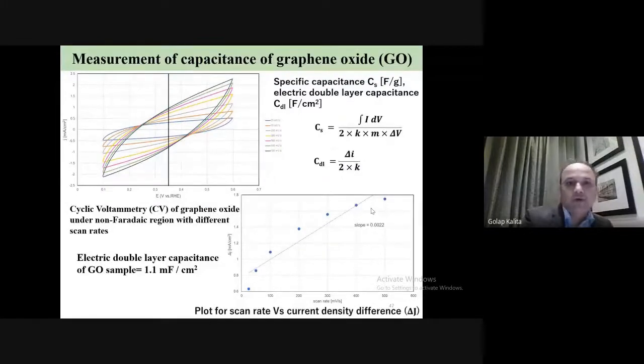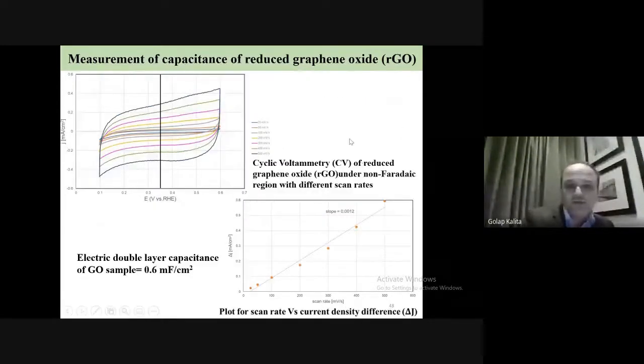Then for the same materials, GO and RGO, we studied the capacitance measurement, and you can measure the specific capacitance as well as the electric double layer capacitance by changing the scan rate for the CV. We measured from 25 to 500 millivolts per second scan rate. In the middle, you see the difference of current, delta I. If you plot this versus scan rate, you can find the electric double layer capacitance using these equations. This is not so high at present for RGO, while for GO we get a much higher double layer capacitance.